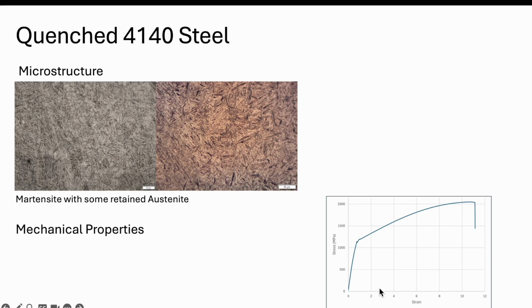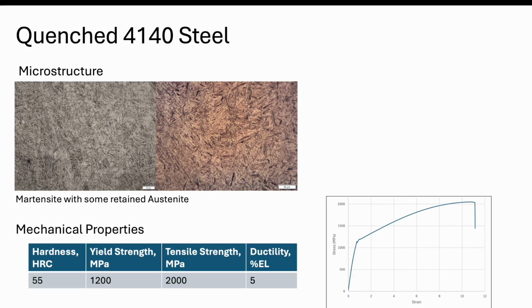Here's our engineering stress strain curve. We have the elastic portion and the plastic portion. When we look at 4140 steel that's quenched, this is going to be the most extreme of the samples. So it's going to have the highest hardness. Rockwell on the C scale is going to give us a value of about 55. This can change depending on what type of quenching we do, water versus oil and so forth, but we tend to get somewhere in the 55 range. This is very hard. This is typically a value that you'll see on cutlery and other fine knives.